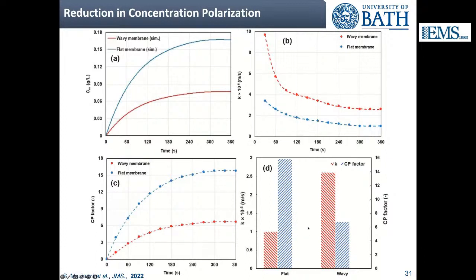So in fact, the wavy membrane can significantly reduce the concentration polarization when dealing with charged probe molecules. Again, remember, the flat membrane and wavy membrane both have the exact same selective layer, which is a PVDF polydopamine nanofiltration thin selective layer.